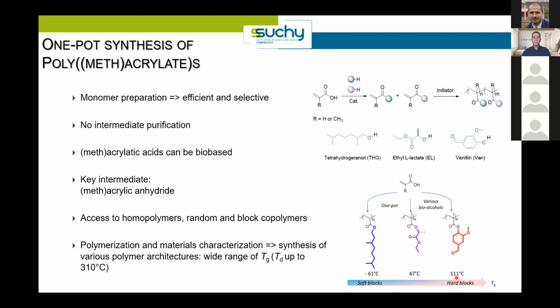So in order to obtain a more processable material, we then decided to investigate a similar one-pot sequence starting from methacrylic or acrylic acid. And again, this one-pot approach makes it possible to directly obtain bio-based materials without needing to isolate or purify intermediates. And to form our monomer, we used bio-based alcohols, such as ethyl lactate or vanillin, which is one of the only industrially available aromatic products of lignin.